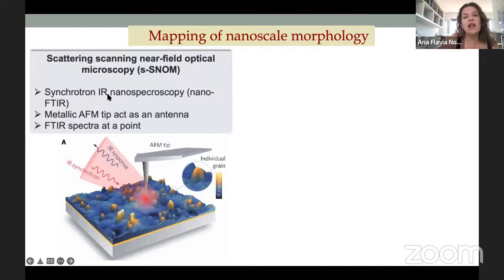In this case, the technique is called, it's easy to say, nano infrared. But the correct name is scattering scanning near field optical microscopy, because we are generating a really strong field with a really high resolution of 25 nanometers. Then you have your sample here. This is the AFM tip. So the infrared light is reaching the tip of the AFM, and what we are detecting is the scattering of the infrared light.